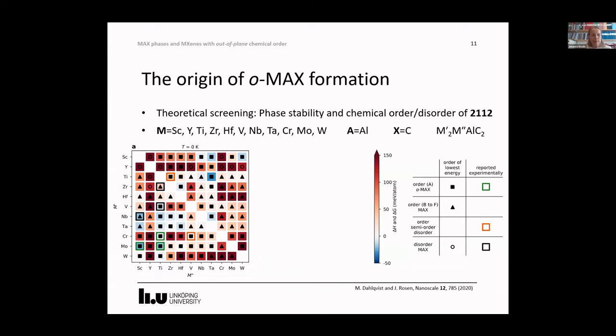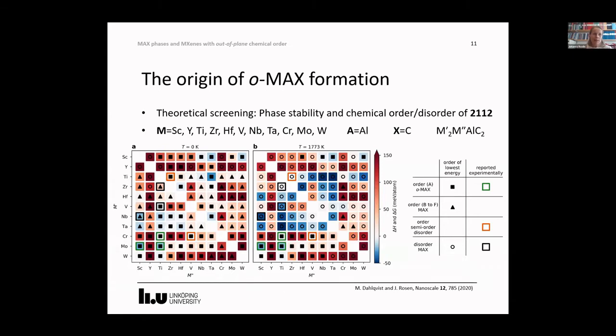But since typical bulk synthesis of MAX phases takes place at maybe around 1500 Kelvin, or 1500 Celsius or so, we need to consider the contribution from temperature and entropy, as I mentioned before. Including this, we see that many of the phases predicted chemically ordered at 0 Kelvin are disordered at elevated temperatures. Still, a number of new OMAX phases seem to be stable.